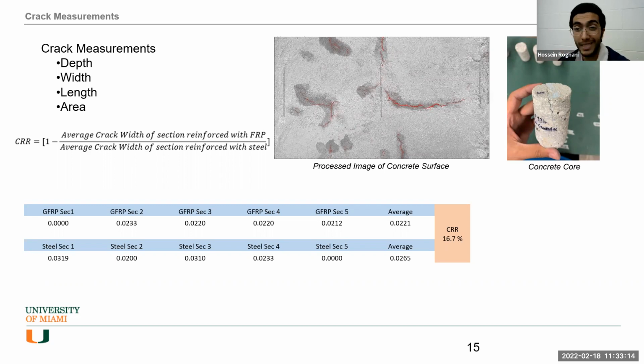And why do we have both of them in the same mold, with a divider at the mid-span? Because we wanted to have both specimens in the same wind tunnel. We wanted to expose them to the same environmental conditions in terms of the wind speed, the relative humidity, and also the ambient temperature. So it was very important to put them in the same mold. Each part is divided into 5 sections to capture the photos for the image processing. The image processing software is used to measure the crack width, length, and the area.